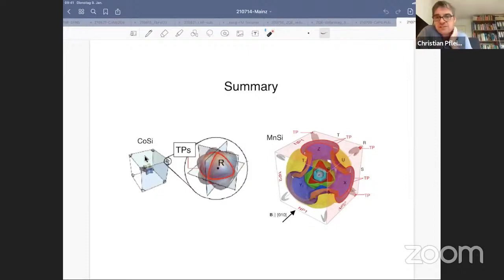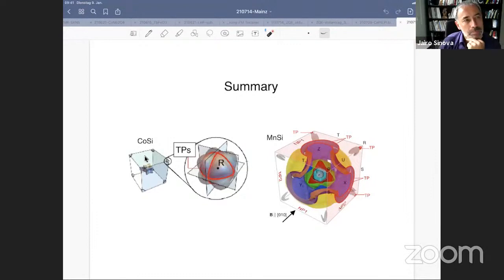I mentioned the crystal quality in two locations of the talk, right? The first one is the requirements for the ARPES studies, and the problem with the cobalt silicon and MnSi is because it's cubic, it doesn't cleave, and so my understanding is because of that, there's difficulties in getting the surface in a way that allows ARPES measurements. Cobalt silicon and MnSi as such grow very nicely metallurgically. So it is possible to grow sufficiently clean bulk samples, and for the quantum oscillatory studies, you need bulk samples. Okay? And then it's in a way also nice because you can really probe the bulk level in the surface and then backtrack what's going on at the surface.